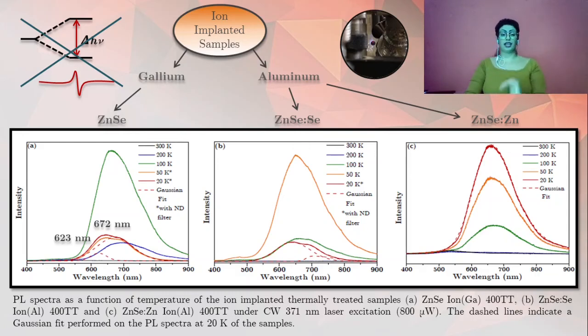So we can associate directly this PL band with radiative recombination of complex defects involving a shallow donor state due to the gallium impurity. The luminescence band observed at 672 nanometers was not resolved for the diffusion gallium-doped sample, but it also can be associated with complex defects involving gallium impurity.